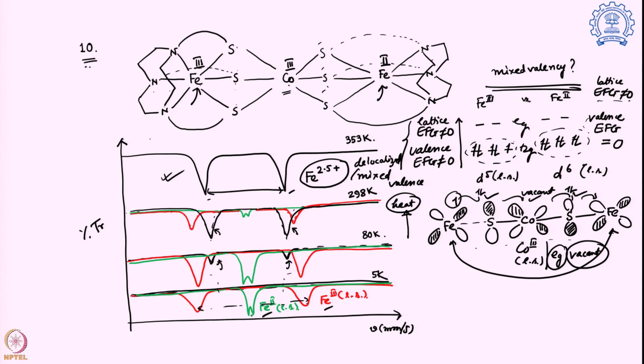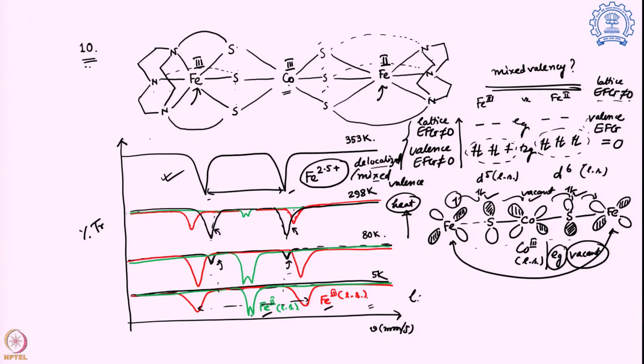So, it shows that only a little bit of option you give to the iron to bridge through the sulfur, cobalt, sulfur to the other iron, it will do that. So, if you want to totally stop it, you have to go to very low temperature, only then you will stop it. Otherwise, you are going to see this interaction. So, over here we can say we are seeing a delocalized mixed system which comes to a localized system only at very low temperature.